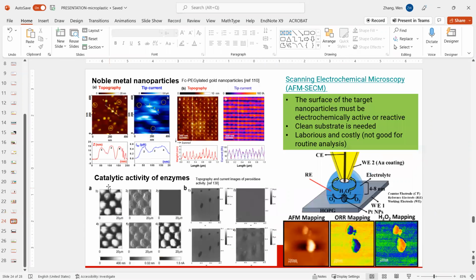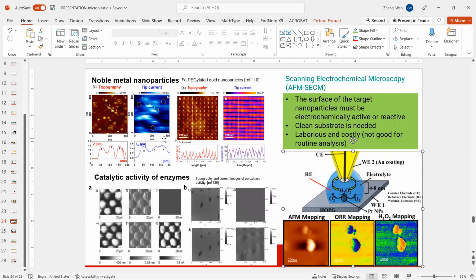For example, this is some of the literature data, even though it's not directly related to polymers, but it is useful. If you look at the data, they use noble metal particles. Again, not merely looking at the particle shape and size, but we can also tell their reactivity. Some of the particles might be more reactive. You can see the tip currents are higher or lower depending on how you run these electrochemical measurements. So then you can largely differentiate the samples from somewhere else.